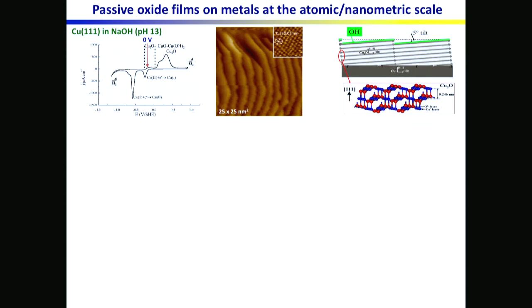Now we know, and this is not from STM, it's because we are always combining STM with XPS and other surface analytical techniques, but we know from XPS, and some others have also found, that there is a layer of hydroxy groups adsorbed on the surface. And this is very important because an oxide often has a fairly high surface energy. This is not really the case for copper oxide, but we will see in the next example that the surface energy of the oxide growing is very high, and the oxide should not be stable.